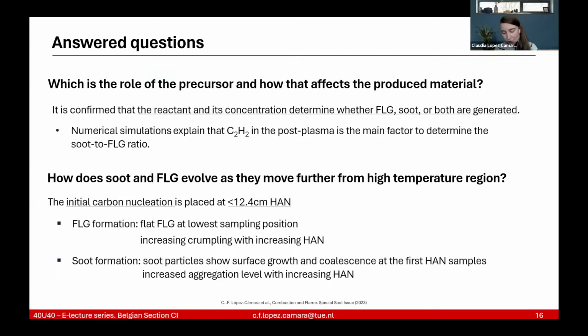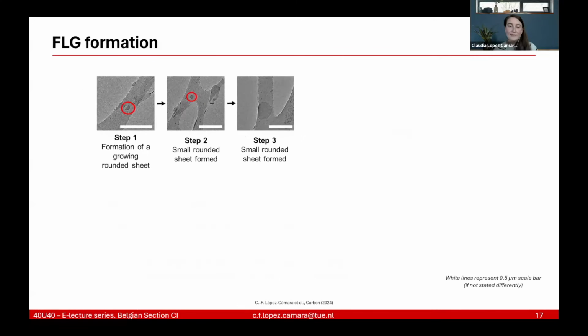So with that, after so many hours being spent in the TEM, I was starting to see some patterns, actually. That was an unexpected observation. And I thought, well, this might explain a story, because these patterns are repeated and repeated. And I saw so many pictures, and so many samples that we did for that work. And therefore, I pitched this hypothesis to my colleagues, and we actually checked it out as well. So I pitched a hypothesis for few layer graphene formation, and that consists of the following.